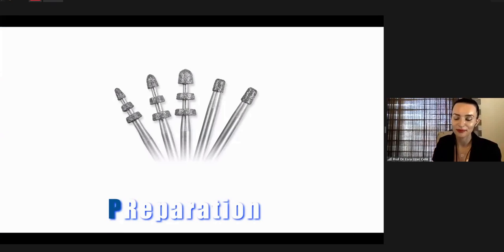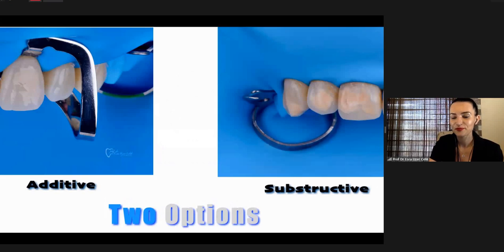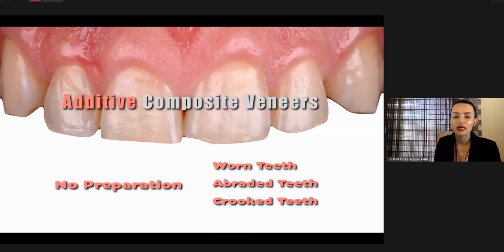And the preparation step. The next one is the preparation step. Different from indirect composite veneer restorations, preparation is not obligatory. So there's not a standard preparation depth for composite veneers. It depends on the etiology. There are two options for the preparation for composite veneers. You may use additive techniques, or you may use subtractive techniques for direct composite restorations. In additive composite veneers, we just roughen the surface with a fine diamond bur to remove the outer hypomineralized part of the enamel. And we use this technique for worn, abraded, or crooked teeth.